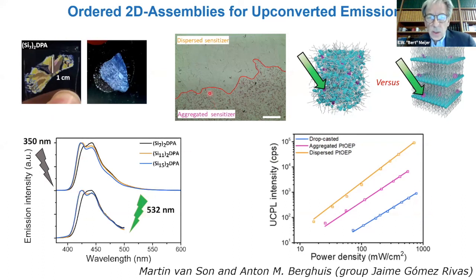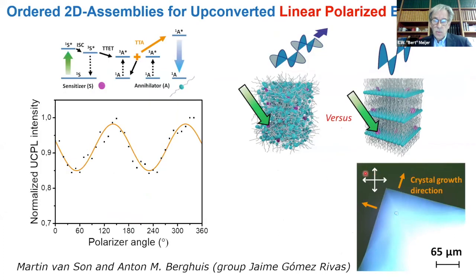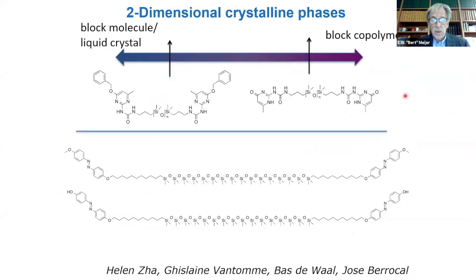But what is more important, if you disperse the sensitizer well, it actually goes much better. And we can make now centimeter long white areas in which it is perfectly dispersed and perfectly aligned. And with that, together with the group of Jaime Gómez Rivas, we're even able to make linear polarized emission coming in with non-polarized light. So this is due to the perfect alignment of these structures. So I think it gives it a possibility to use it as a material.